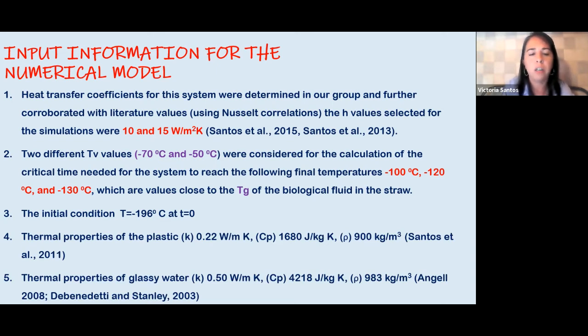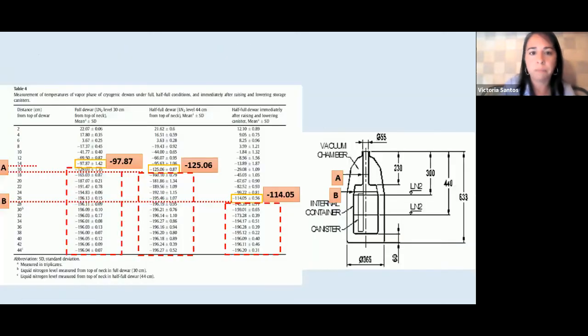The initial condition, well, it was submerged in the liquid nitrogen. It was -196 degrees at time T equals 0 seconds. And we have the thermal properties of the plastic and the thermal properties of the glassy water. All of these properties are involved in the governing heat conduction equations.